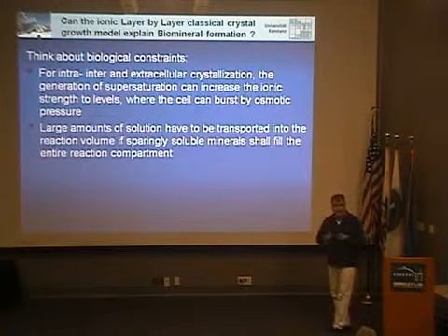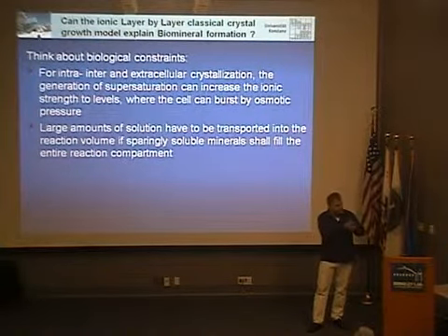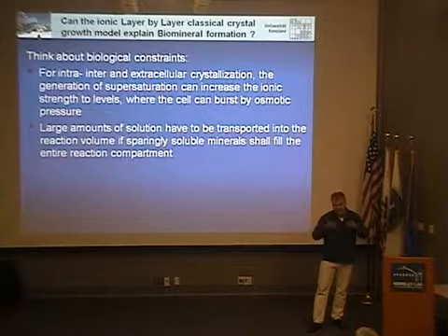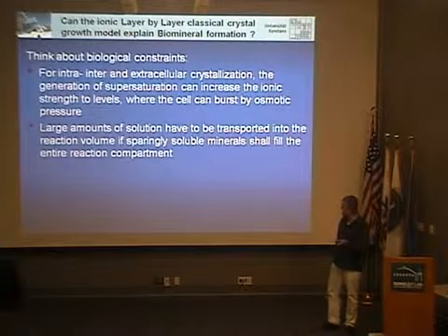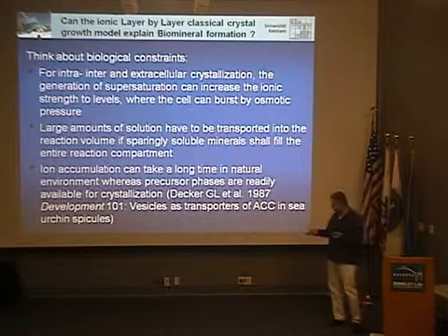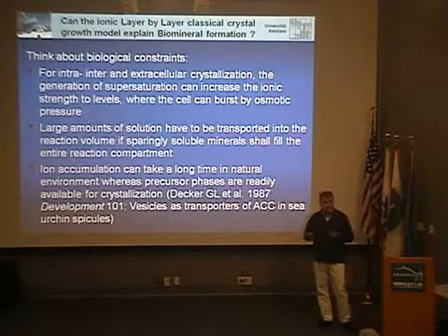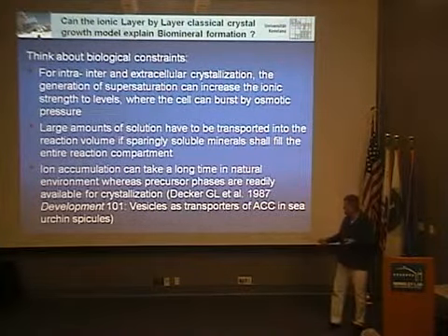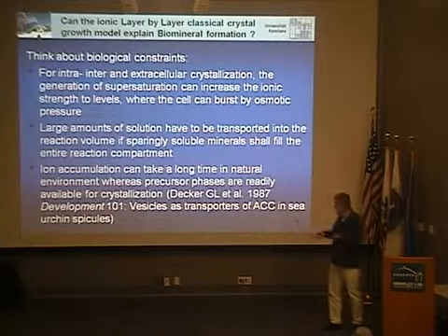The other thing is, if you've got a sparingly soluble salt and you want to crystallize that as a biomineral, you have to transport large solution amounts through the cells to sequester enough ions to get over the supersaturation limit to finally precipitate the biomineral. So that's also not advantageous. So that results in the fact that ion accumulation can take a very long time until you precipitate something in a natural environment.